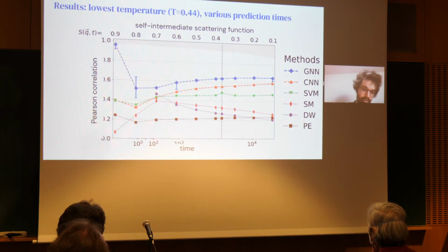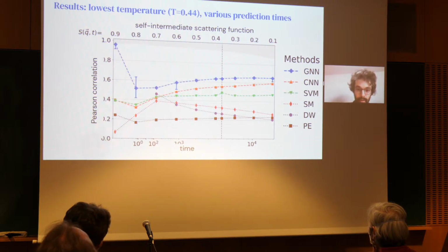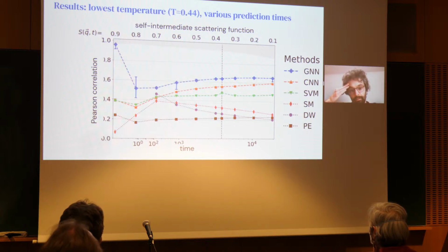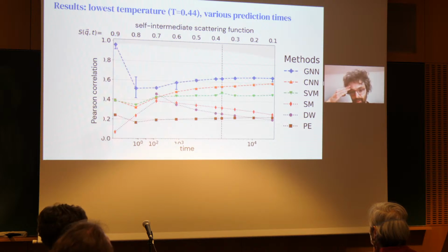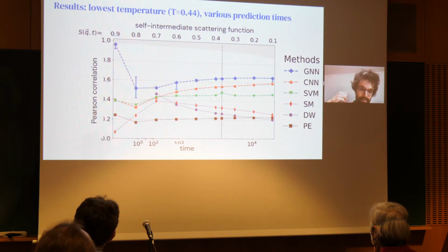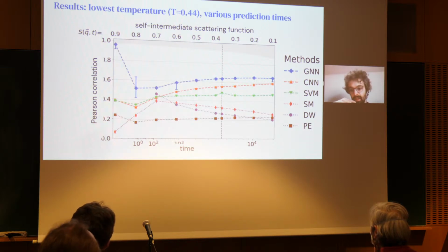So this is reporting the correlation as a function of the time for a fixed temperature, the lowest temperature. The vertical line is the alpha, and you can see that the method proposed here, the blue one, is above all the others in terms of the correlation. It does, as you'd expect for a very short time, reach perfect correlation, then it decreases and it increases again, interestingly, as you increase the time. The physics-based methods are the three at the bottom. So the performance is optimum for a short time scale.